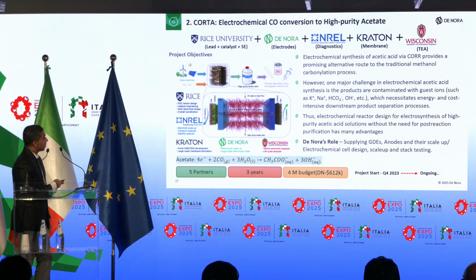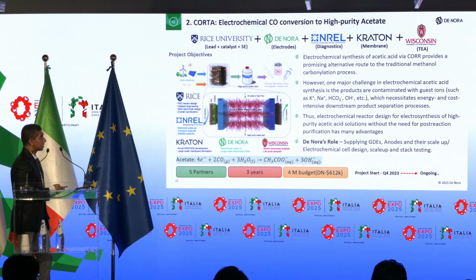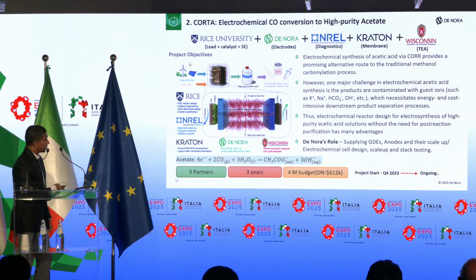As I mentioned, the goal of this project is to make high purity acetic acid. Acetic acid is a very important chemical precursor in industry. As I mentioned in the previous project, one of the main challenges in the electrochemical production of acetic acid is that typically the product is contaminated with guest ions such as potassium, sodium, bicarbonate or hydroxyl ions. So what we need to do is engineer the system such that we can minimize this ion contamination. As a result, we came up with this cell configuration.